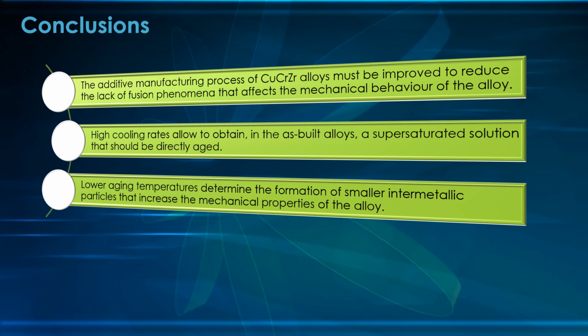In conclusion, we can see that the additive manufacturing process of copper chromium zirconium alloys must be improved in order to reduce the formation of defects like cavities and lack of fusion, because they affect the mechanical behavior of the alloy. The results highlighted also that the high cooling rates involved in the production process allow to obtain in the as-built alloys the formation of a supersaturated solution that must be directly aged.